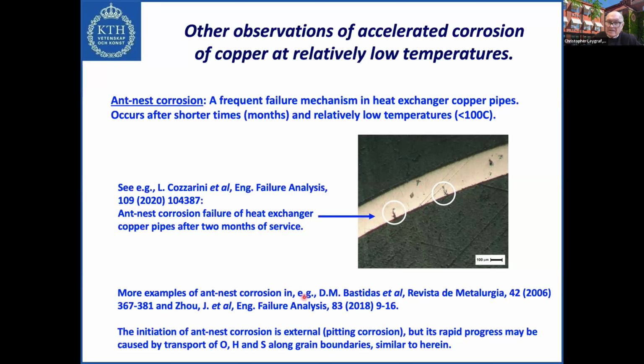So this is actually nothing particularly new, but the mechanism is a little bit different. The initiation of ant nest corrosion is from the outside. It's external, so it's like pitting corrosion. But the rapid progress that makes this go so deep into the material in a few months, and we see here typically maybe 100 micrometers into the material, is that the ant nest corrosion may also be facilitated by the rapid transport of oxygen, sulfur, hydrogen, and so on into the material at the elevated temperatures, like we have seen here.